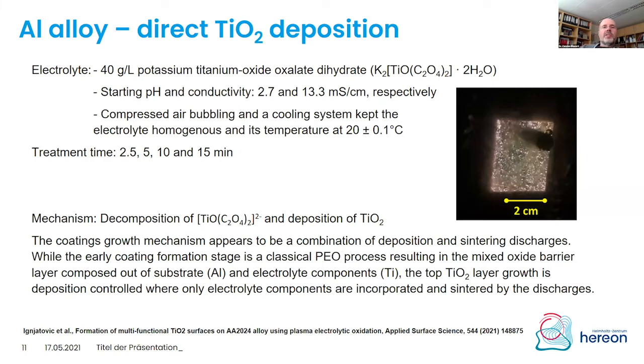Actually, it was even a surprise for us, because with this electrolyte we have deposition of titanium dioxide, which obviously comes from a decomposition of the oxalate, the titanium oxide oxalate complex. And that gives us the chance to actually get pure titanium dioxide layers on aluminium, where with standard electrolytes we would normally expect the treatment to give us aluminium oxide as the main phase. But here it is different.